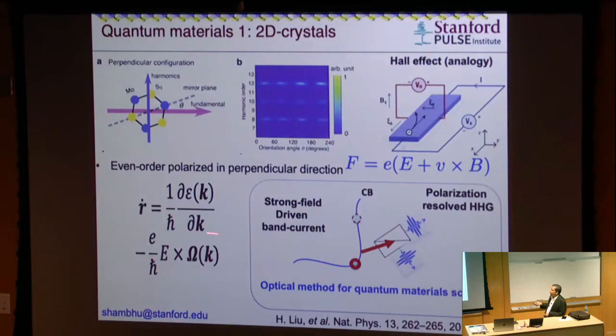it acts like, because of the interesting symmetry properties of the crystal, the electron here acquires the transverse motion in the band. Okay, so we argue that since it was driven in the transverse direction, the polarization is also in the transverse direction, and it's actually with that theory. In the quote-unquote theory, in a semi-classical description, you actually have an interesting approach. If you put a cube polarizer here, since the harmonics are in the visible range, you just have a way to do a polarization spectroscopy, and you have a way to probe the moving electron in a band, and probe the dynamics in the orthogonal direction.